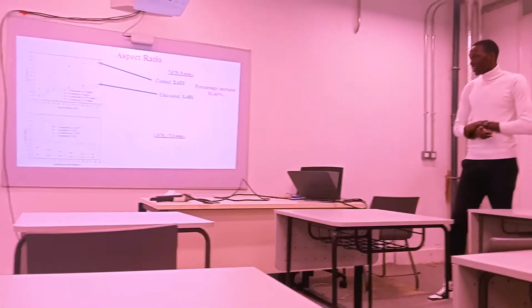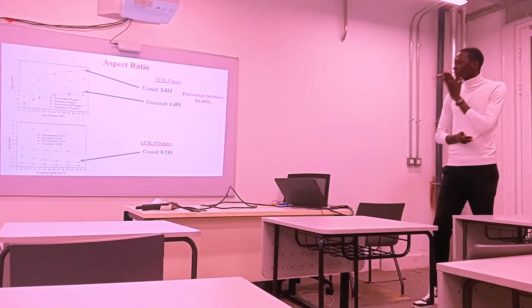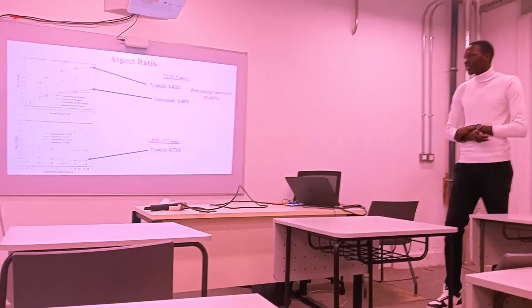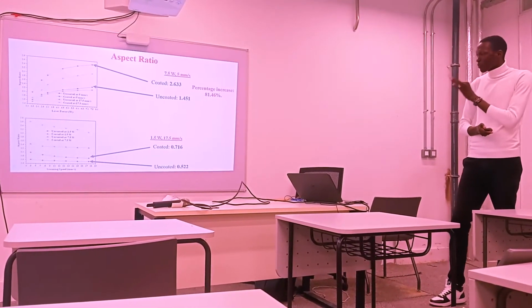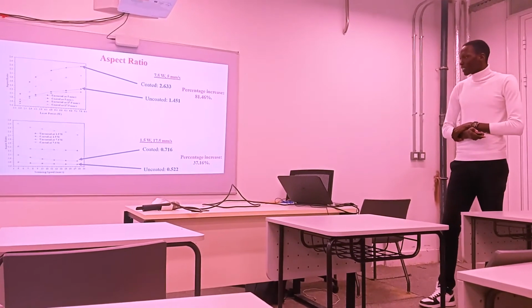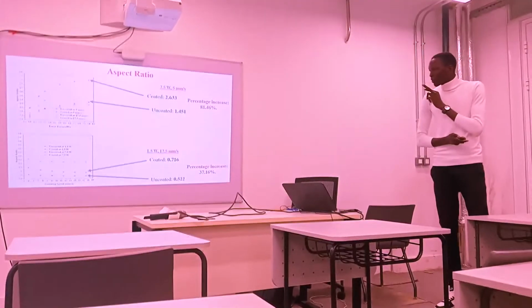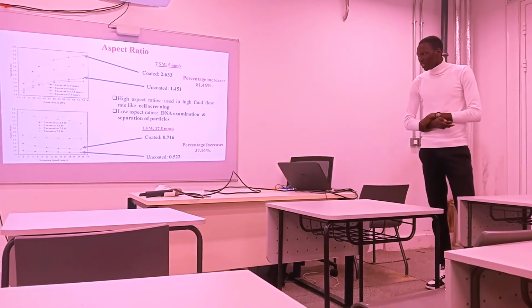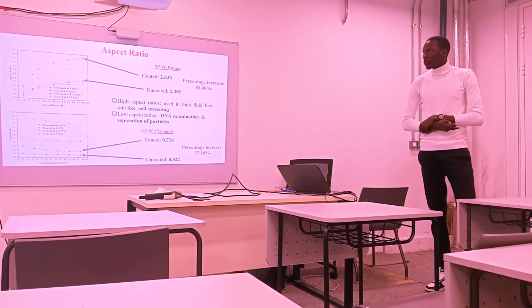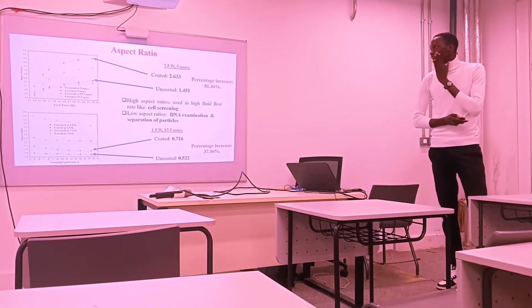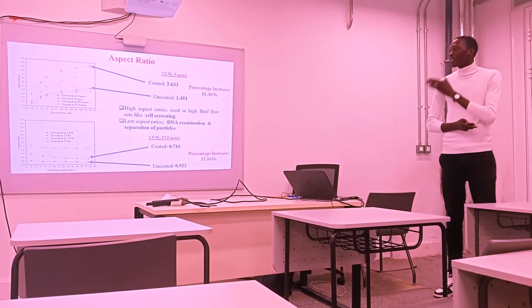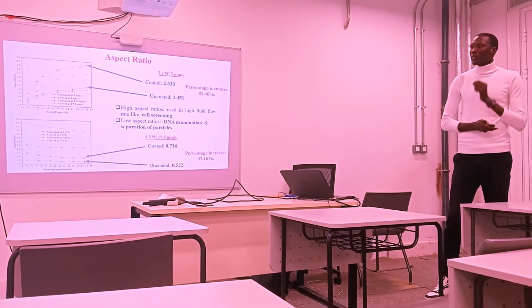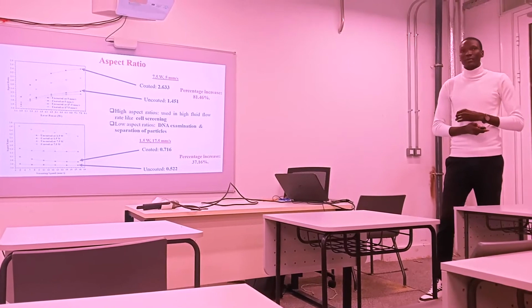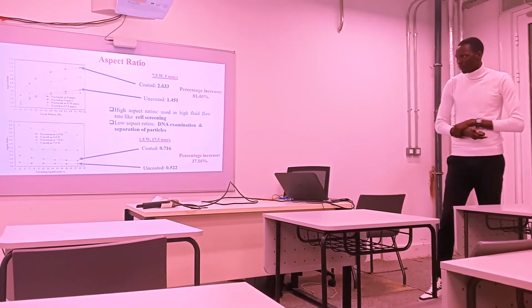At minimum power and maximum speed, we got aspect ratio to be 0.716 for the coated. Then for the uncoated, it was 0.522, a percentage increase of 37.16%. Now, high aspect ratio values are required in high fluid flow applications like cell screening, but low aspect ratios are needed in DNA examination and separation particles among other applications.